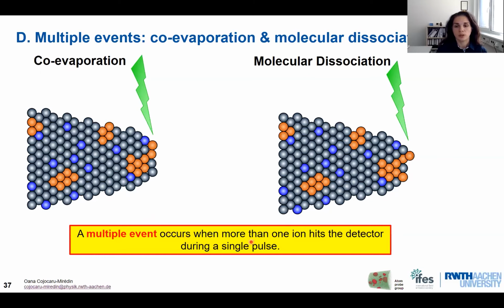Multiple events occur when more than one ion hits the detector during a single pulse. So basically, when we have a pulse, we have not only one ion which is field evaporated, but several ions, two or many ions evaporated and then collected on the detection system. So there are basically two processes. The co-evaporation process, which is simply the fact that when the laser hits the tip, we have the field evaporation of two or many other hits, and the molecular dissociation process, when the laser hits the tip, we have a molecule which is field evaporated, and during the path, this molecule is going to dissociate, and very often we end up having multi-hits on the detection event histogram.